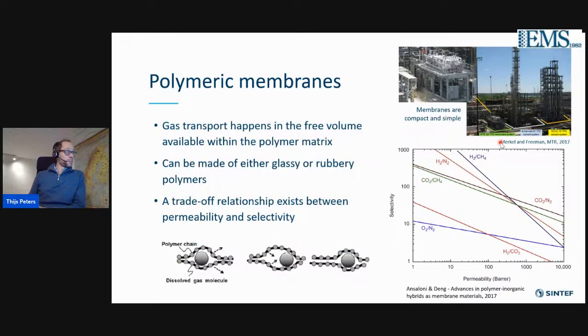I will start with the polymeric membranes, where the gas transport happens in the free volume available within the polymeric matrix. This polymeric matrix can either be made of a glassy or a rubbery polymer. Depending on the material, they can be selective, for example, for CO2 over methane, oxygen over nitrogen, hydrogen over CO2.